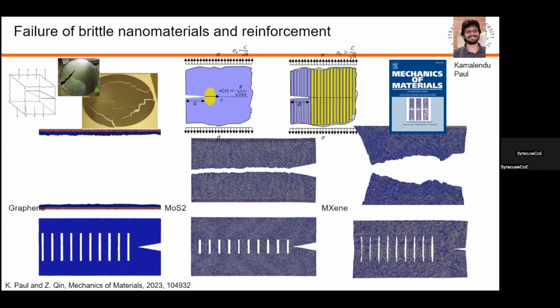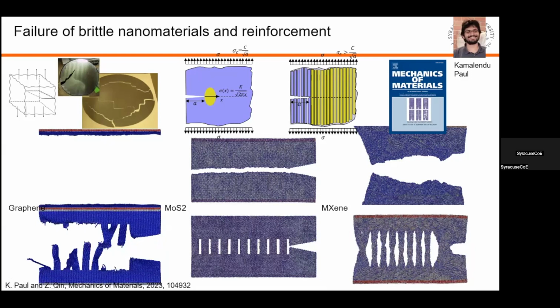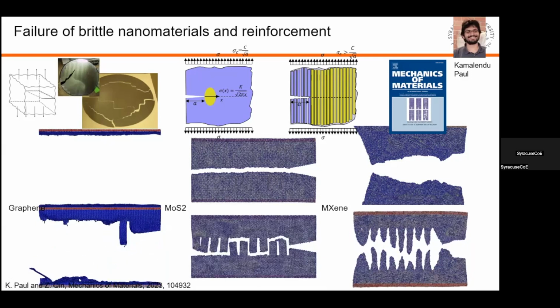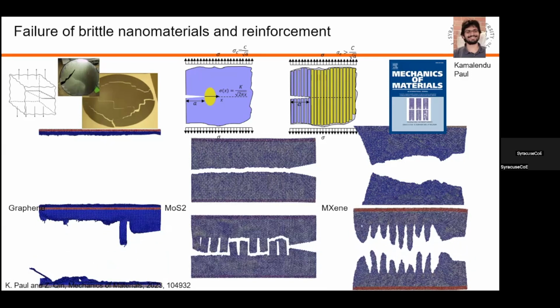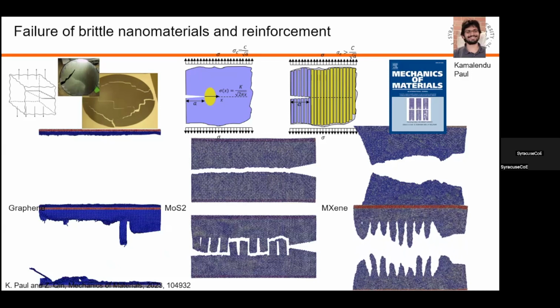Here is the comparison for the simulation movie. I just quickly click all three to see that once you have a crack, the crack will not instantaneously propagate in a straight line, but it will go around each of these bridges and tend to break those bridges instead of causing catastrophic failure. That's a work we recently published in Mechanics of Materials, and it was also selected as the cover image for this paper.